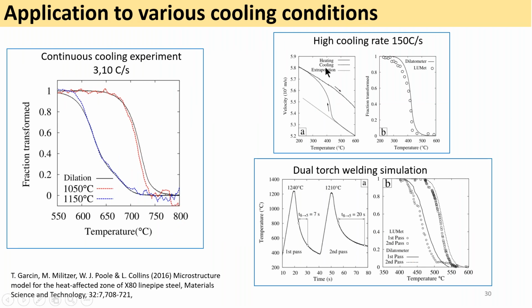I want to show you here a different type of cooling condition to show that, because we have a high repetition rate for this sensor, even at a very high cooling rate, 150 degrees per second, we still have very good agreement between the velocity signal measured using Lumet and the dilation measured using dilatometry. This can be applied to dual torch welding simulation as well, where we have the austenite decomposition occurring during the first cooling and the second cooling here as well. Very good agreement during this test.